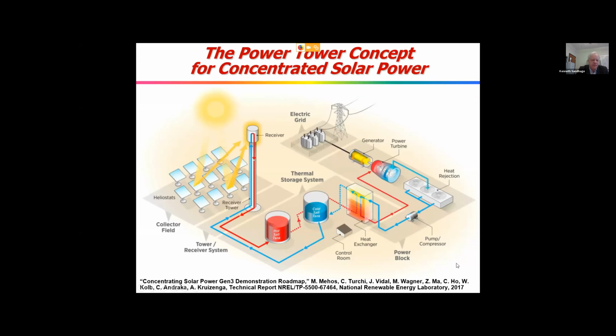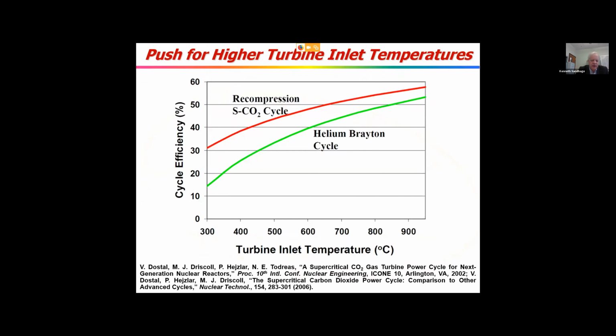And so to get this type of an approach to be more cost effective, to reach parity on cost for electricity with fossil fuel derived electricity, one of the key steps that has to happen is to get the system to operate at a higher temperature, to be more efficient in converting sunlight heat into electricity. And so one of the challenges in doing that is the heat exchanger that's used for this type of a process. As I mentioned, prior authors from MIT, in fact, have shown nicely in a number of papers that by increasing the turbine inlet temperature in this type of a turbine application, the efficiency converting heat into electricity can be significantly improved. What you see here are two curves, different working fluids, supercritical CO2 or helium, different locations for the curves, but the trend is the same. As you go up in temperature, the efficiency goes up.